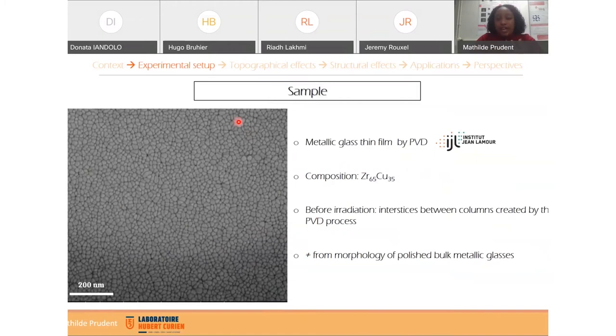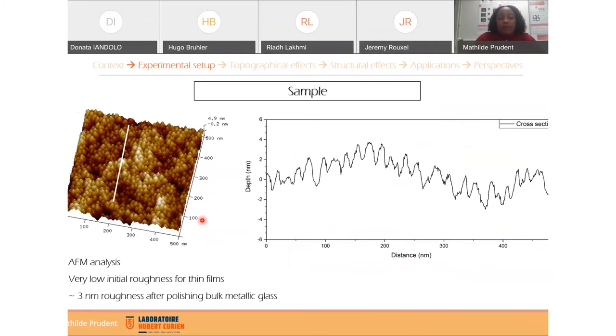Here you can see that before irradiation, we can see some interstices between columns created by the PVD process. And this morphology is different from the initial morphology of bulk metallic glasses after polishing. However, after AFM analysis, we just extracted here a profile line of roughness, and we can see that we have a very low initial roughness for the thin film also, less than 10 nanometers. It's approximately the same order in comparison to the average roughness obtained after polishing for bulk metallic glasses. This roughness was approximately 3 nanometers for bulk.